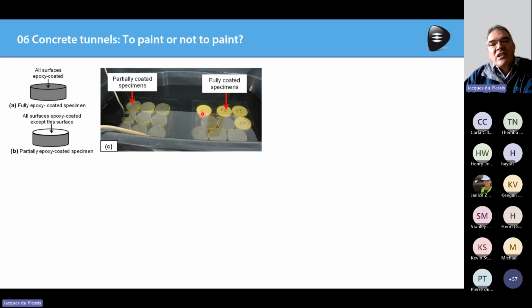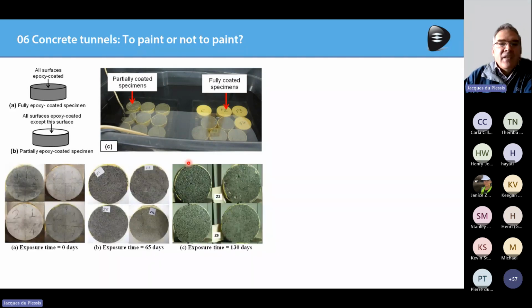And then some of those samples were fully coated. Then the water was circulated continuously over these specimens. And then every week or so, a lab manager would go there with a brush and he would brush it lightly, just to mimic the abrasion inside the tunnels. And there you could see the effect after 65 days, after 130 days.